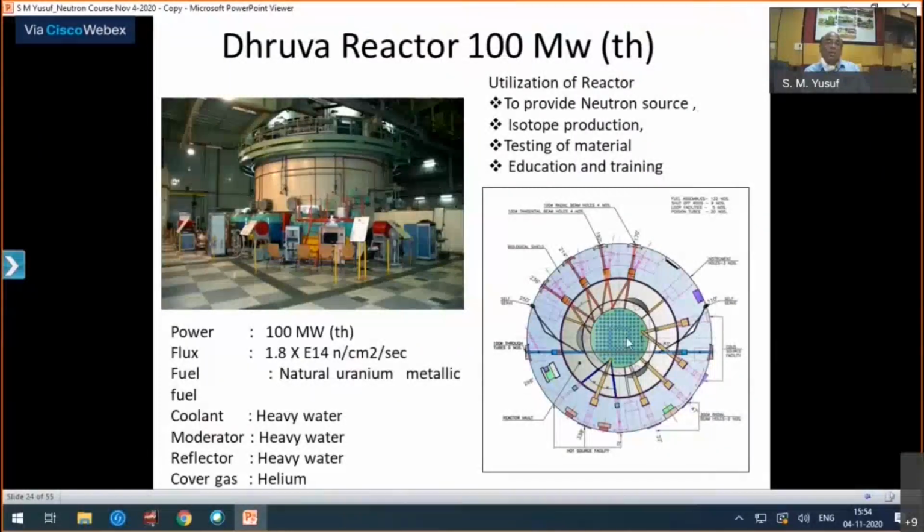That is nothing but the inelastic process through which you reduce the energy of the neutron from mega electron volt to milli electron volt, and those milli electron volt neutrons come out from this reactor through these beam holes, and you set up different experimental facilities all around. And you already know why you need milli electron volt energy? Because for milli electron volt neutron energy, if you calculate the de Broglie wavelength, lambda equal to h by p, you will end up getting lambda typically 1 to 1.5 angstrom. So that is the requirement.